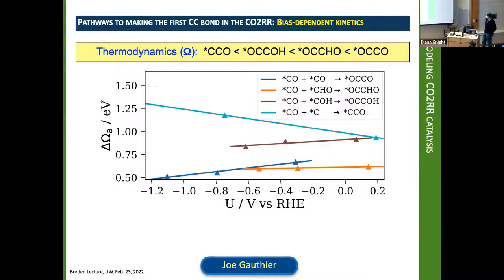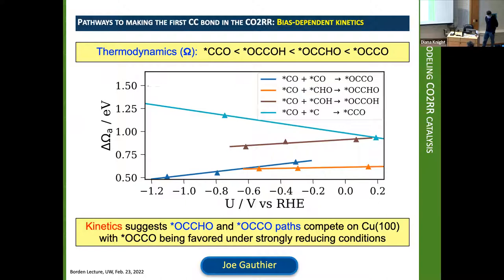And surface-bound carbon actually becomes less favorable, less feasible as we go more negative in voltage, whereas the CO recombination becomes more favorable. So it looks as though, in fact, thermodynamics is not what dictates the outcome here. Kinetics suggests it'll be CO dimerization, and again, this is not a full so-called microkinetic model, this is just looking at elementary steps. If *CHO is there, it will also compete, especially at relatively low biases.